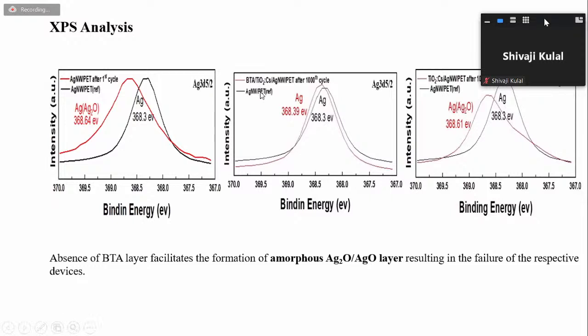In the case of the benzotriazole-added silver nanowire, even after 1000 cycles, it's a stable network and it's still in the silver state. This proves that benzotriazole protects the silver nanowire in the electrochemical reaction, which allows us to use the silver nanowire in the smart window, which can replace indium tin oxide in the future due to its disadvantages like high cost, inflexibility and brittleness.